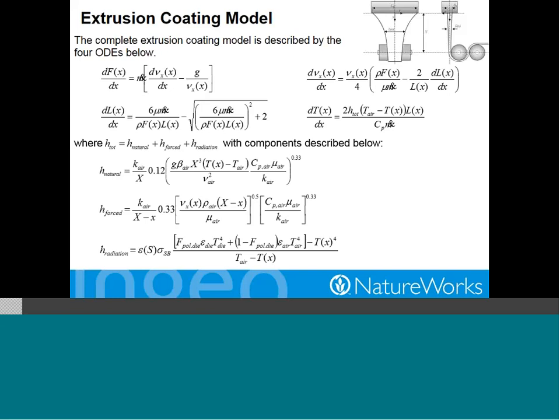The paper stock is typically moving much faster than the melt curtain, and so the material coming out of the die is being drawn down as it's applied and adhered to the paper. And then there's a whole bunch of temperature dependencies as the material comes out from the die lip at its extrusion temperature, and then through the air and going over the rolls. There's some heat loss and things like that going on as well. And temperature plays a critical role in all of this, because viscosity of PLA is very sensitive to temperature, and the viscosity of the material is important in this neck-in process and in the adhesion and adhesive process.